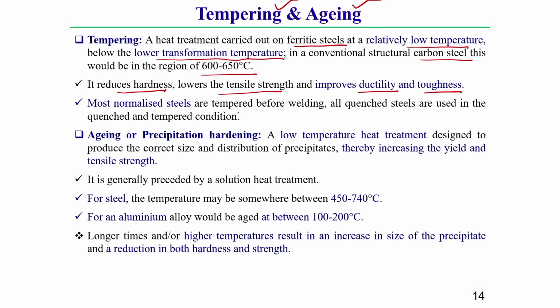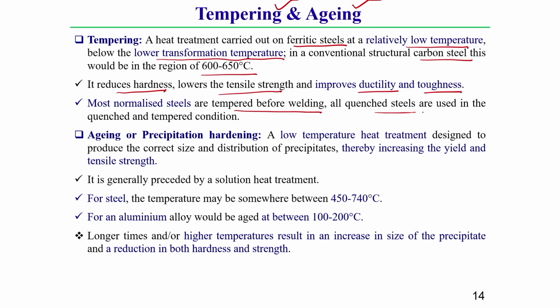One thing you should keep in mind: whatever steel is normalized generally needs to be tempered before welding. So, before the welding operation, the normalized steel needs to be tempered, and after that you should go for welding. Apart from this, quench steel is also first quenched, then a tempering operation is required, and after that we do the welding operation. That is why I have written that all quench steels are used in the quenched and tempered condition. This you should also keep in mind.